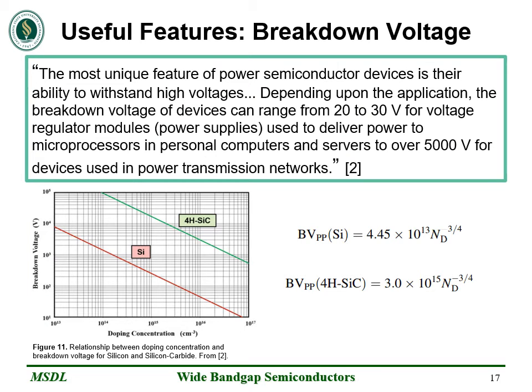We're going to take a moment to look at that breakdown voltage we talked about, because the most unique feature of a power semiconductor device is its ability to withstand high voltages. And this can range anywhere from 20 volts to 5,000 volts, depending on the application. In figure 11, we see a depiction of doping concentration versus breakdown voltage. When comparing silicon to silicon carbide, we can see that it takes roughly 2 orders of magnitude less doping concentration on the lighter dope side of the junction for silicon to reach the same breakdown voltage as silicon carbide. And now, this lower doping concentration is going to prove critical when we look at things like temperature and for depletion widths and on resistances later on.